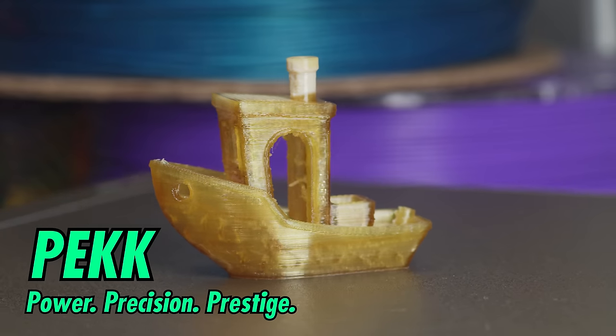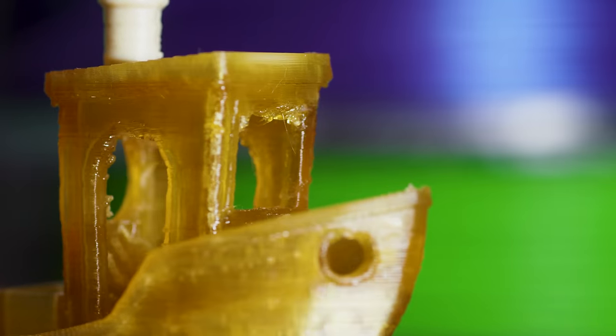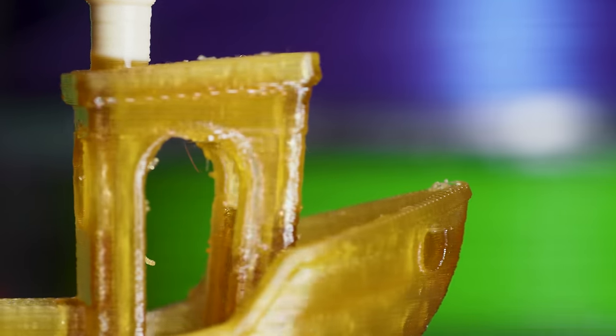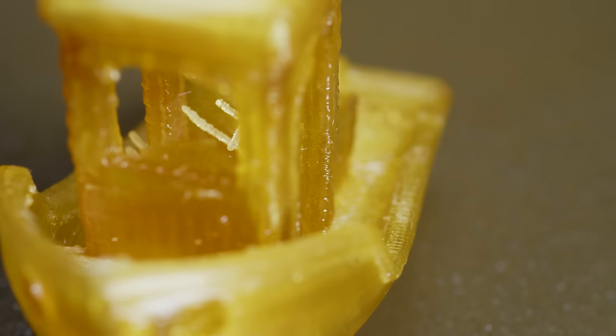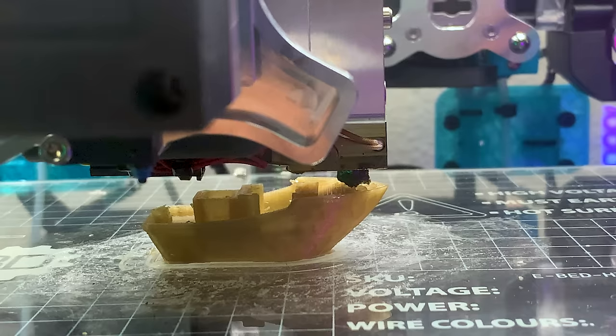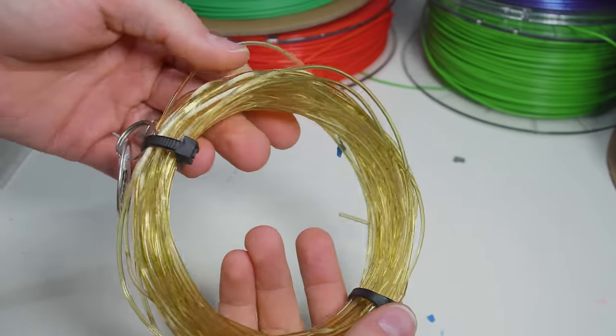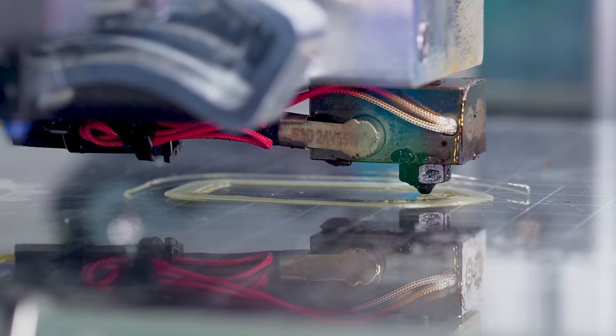So what is the most expensive filament? That dubious honor goes to PEEK's brother, PEKK. Polyether ketone ketone is made of the same building blocks as PEEK, just arranged in a different order. PEKK nearly matches its older brother's strength and resistance to chemicals, and even has a slight edge in terms of heat deflection. It does need annealing to tap its true potential, and as it warms, you get to watch it shift from a glittering crystal-clear to a milky opaque — a property I don't think I've seen in any other filament. PEKK prints slightly cooler than PEEK, and you can run it a little faster.